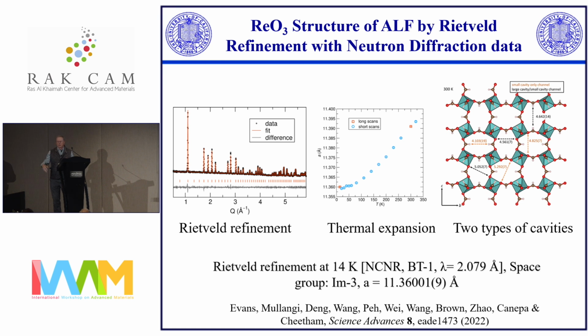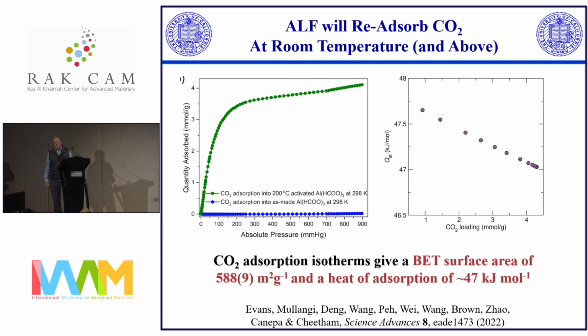We did it as a function of temperature. And so this has nothing in the cavities. It's a bit more complicated than I described so far because there are two different types of cavities. There's a slightly smaller and slightly larger cavity, and I'll mention that later. And then we found it will reabsorb carbon dioxide, and it will do it at room temperature, it will do it at higher temperatures, and the heat of adsorption is quite substantial, about 47 kilojoules per mole.